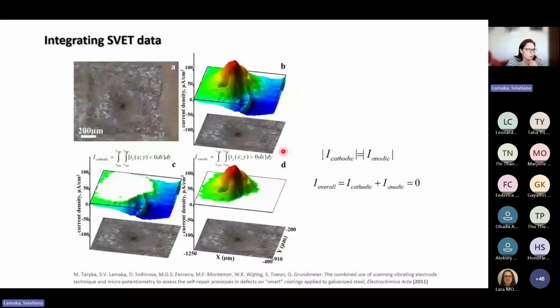SVET indeed is a very powerful method used quite widely in corrosion science, but it provides no information about the ions or molecular species that contribute to the ionic fluxes or chemical reactions. That's why, together with SVET, we use a set of other microprobes, and I will now speak about this. We use a pH-sensitive microelectrode, a hydrogen-sensitive probe for the concentration of dissolved gaseous hydrogen, an oxygen-selective amperometric probe, and an oxygen quenching microoptode.